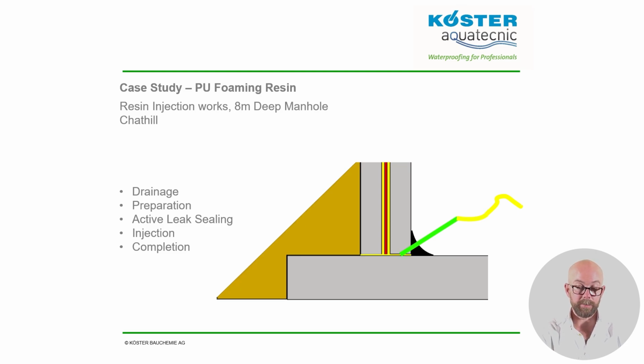A situation had been achieved where no new leakage was spilling onto the floor of the manhole and the injection could be started. The injection was carried out with a fast-setting, elastic, single-component polyurethane. This has a reaction time of about 20 seconds. Each hose was injected in turn.